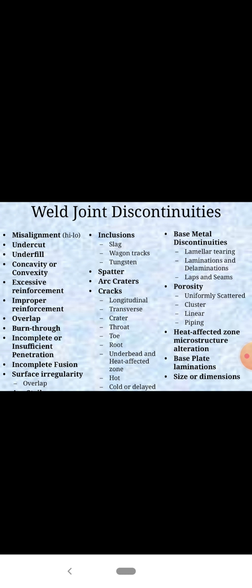And the slag is produced. And also hydrogen is the most undesirable inclusion, causing cold cracking in the steel as well. So shape and size irregularity, metallurgical structure defects, overfilling, poor profile, poor fit-up lead to the lack of fusion, cracking.